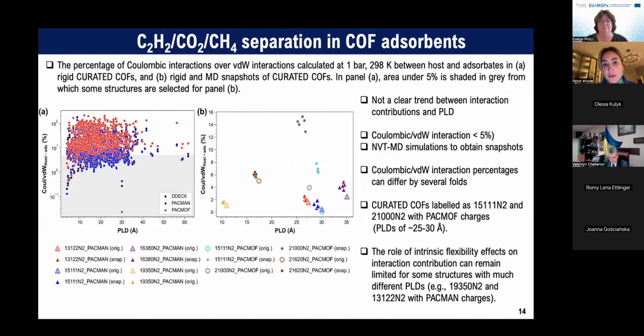In the literature, you can see two ways that we can consider for modeling the flexibility of the structure. One is that you can directly use a flexible structure in your simulations, or you can use a flexible intramolecular force field contribution. Then, using MD simulations, you can generate different configurations, different structures, and then you can do averaging between the results of these different configurations.